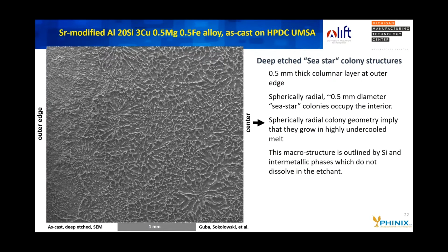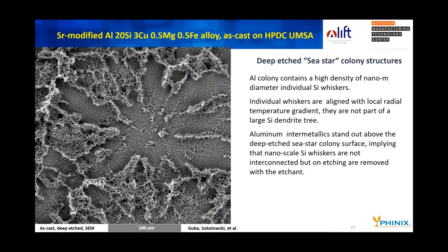On the left-hand side, you have the outer edge of the sample, and you have a columnar growth going into the sample for about half a millimeter, and for the rest of the sample, you have spherical colonies. Those spherical sea star colonies are the main structures.